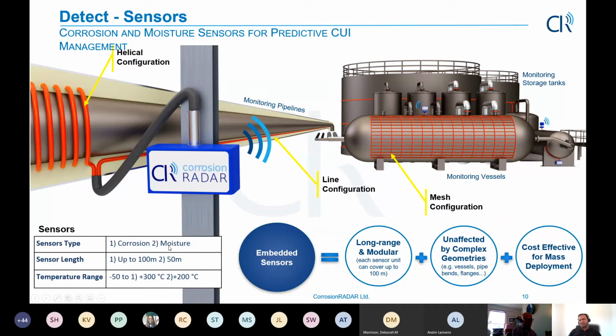So that's on the corrosion, and moisture also follows a similar principle without the sacrificial layer. The moisture sensor does not have any sacrificial layer, no metal component. At a time, 100 meters for the corrosion sensor and 50 meters for the moisture sensor, and up to 300 degrees Celsius capability. So that's on the sensor side.